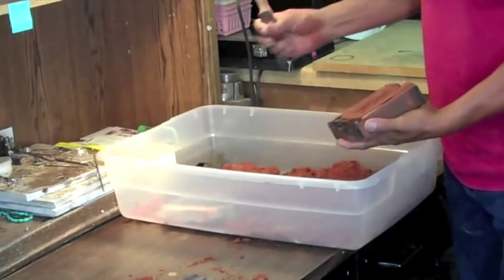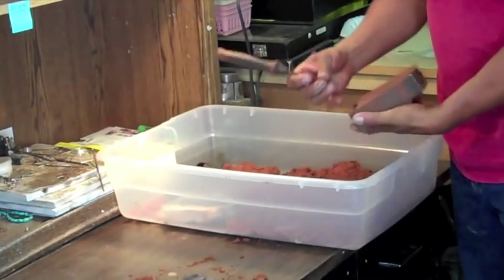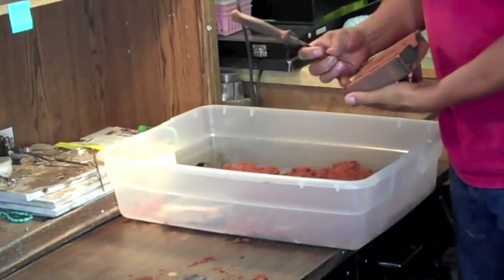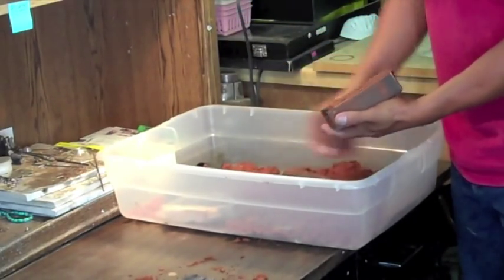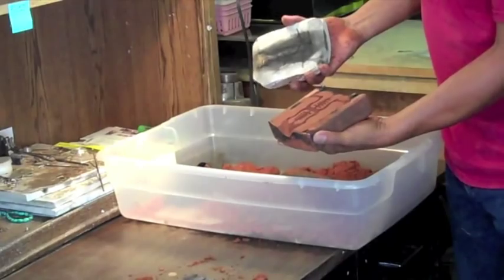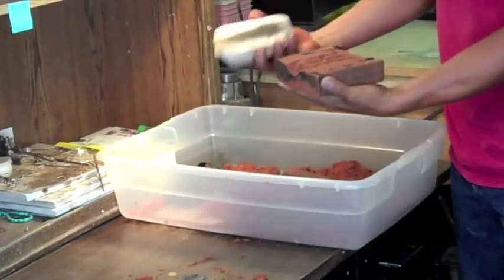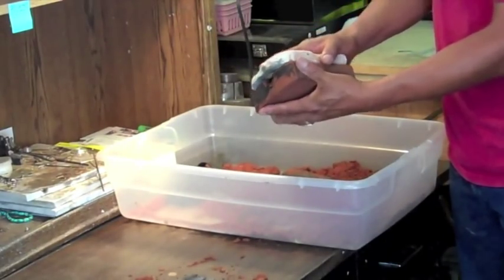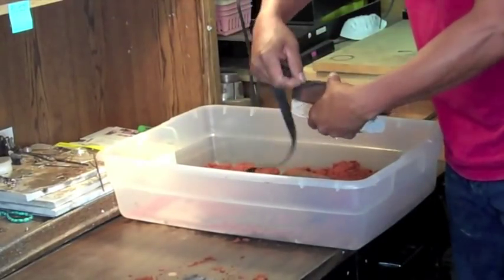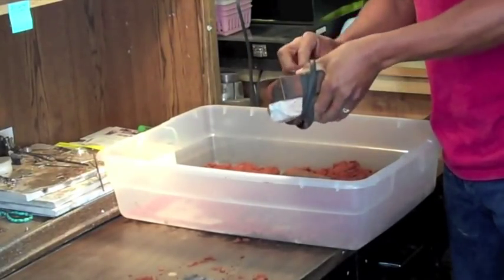Okay, now I would need sprues, just like I did here, for gases to escape. What this does is two things. It helps the gases to escape, and it also pulls the silver down to the bottom of the mold to fill up the channels. And what I do is get a piece of tufa stone, which is already hot, and put that up against here without moving it around. Get your good old Goodyear rubber, tie that around here, and I would stand this up.